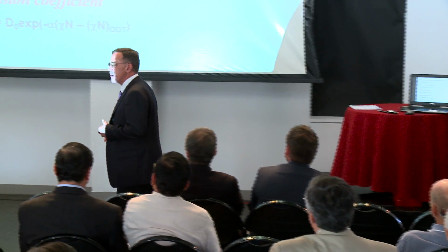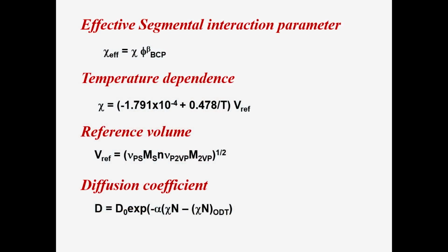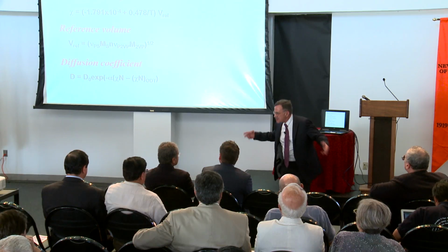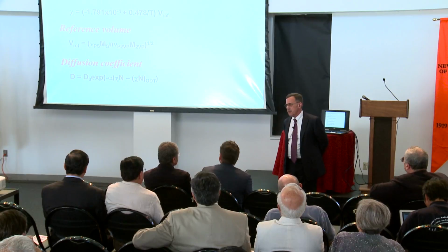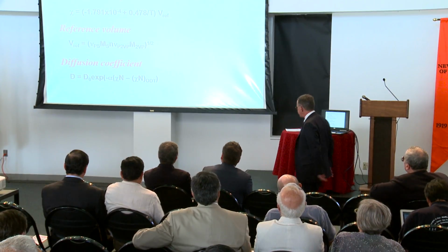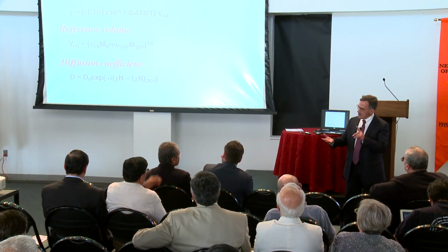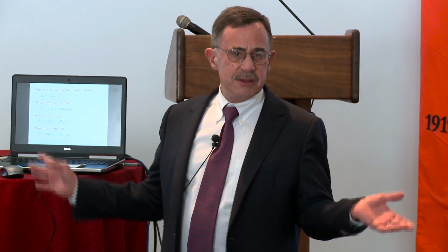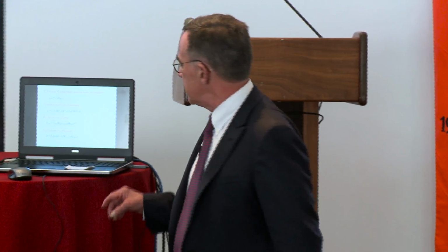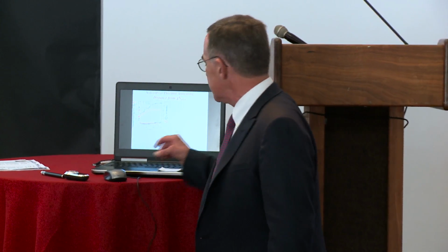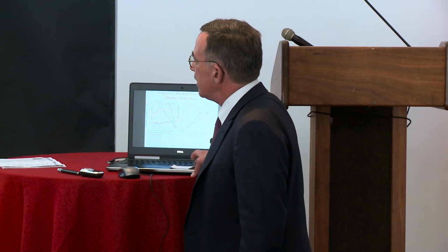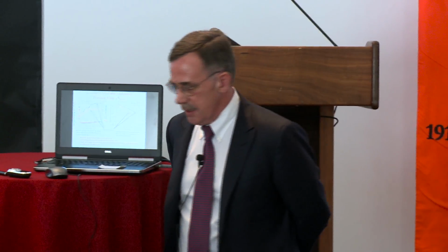So the question is, where do we stand with respect to solvent annealing? We know we can speed up the process. We give you order, but I start to introduce some disorder. Well, how does this compare to thermal annealing, where I don't use solvent, I just heat the material above the glass transition temperature to impart mobility? I can define everything. I define the segmental interactions. I can define mobilities in the system, all of these in terms of diffusion, et cetera, and I can define this quite well. And I can actually do a comparison between the thermal annealing and the solvent annealing.